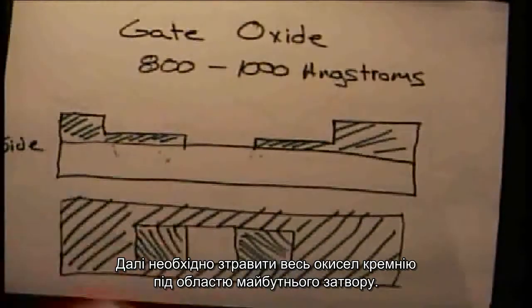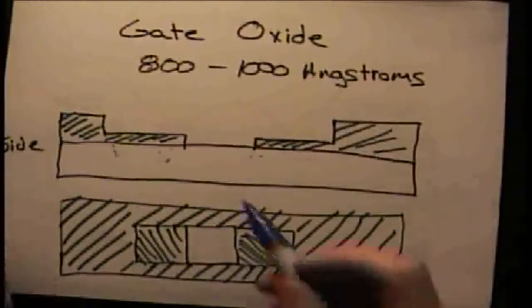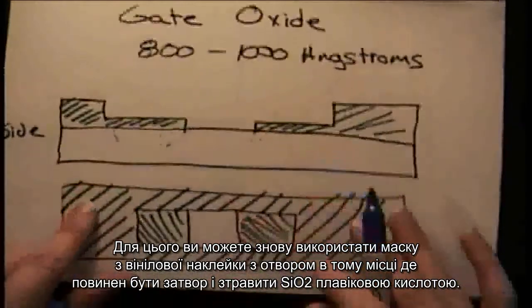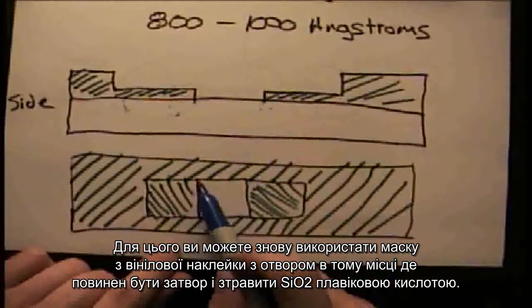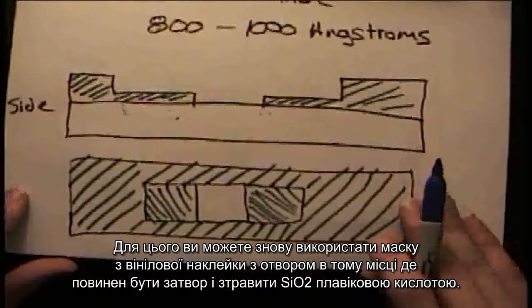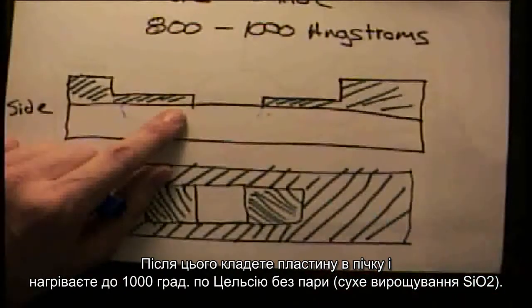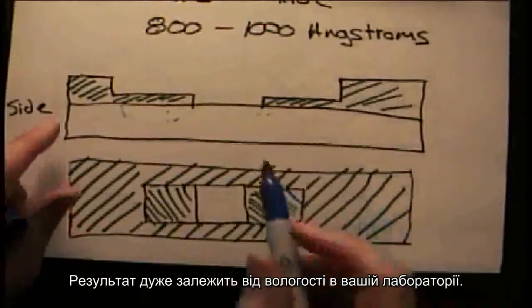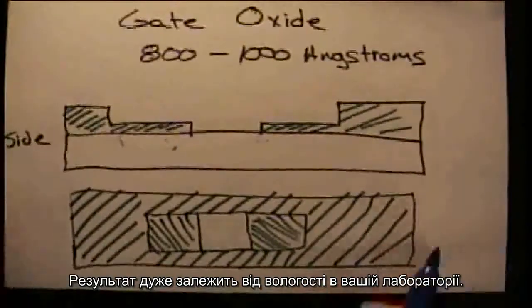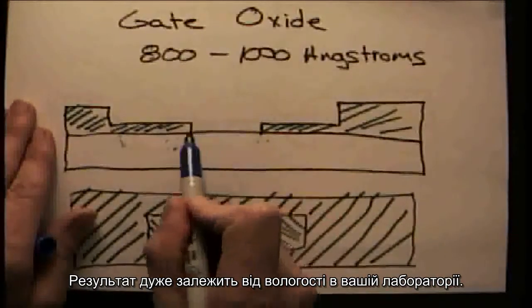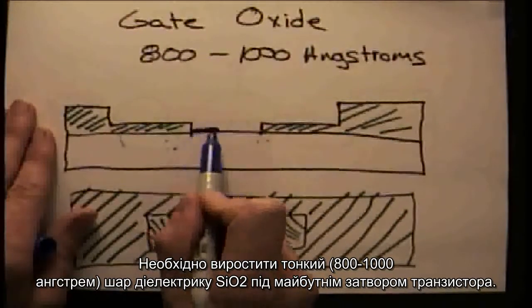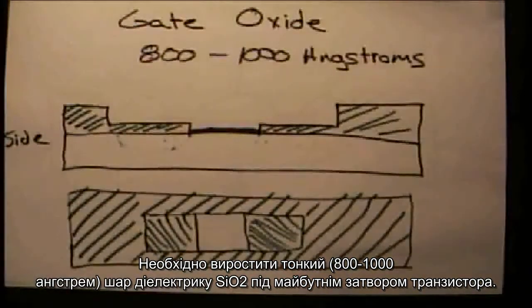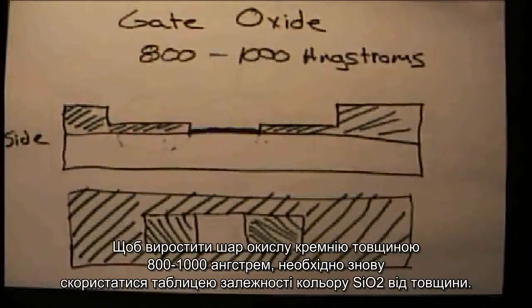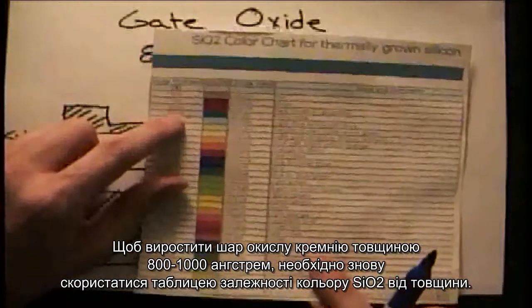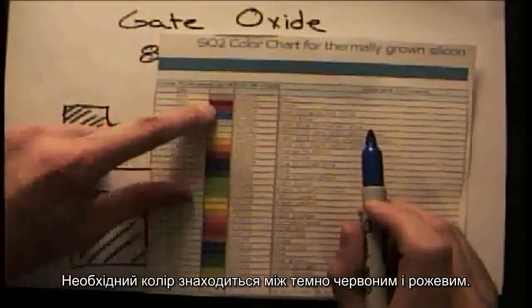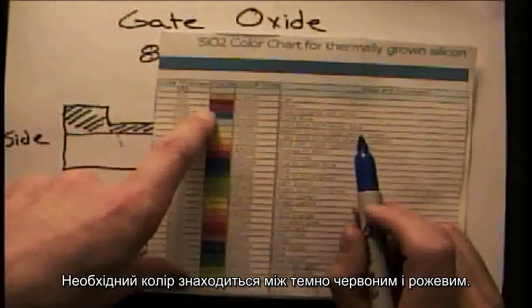The next step is to etch the gate oxide area. So you'll again use the vinyl masks, and you'll open up where the gate region will be. You'll etch this away, wait for it to be hydrophobic again, and you'll put it into the furnace at 1,000 degrees without steam. And this will vary depending on how much humidity you have in your lab at the time, or your house, or your kitchen. And you'll grow a thin layer across. So shooting for 800 to 1,000 angstroms, if you look at the color chart again, it will be between a kind of dark red and pink color.